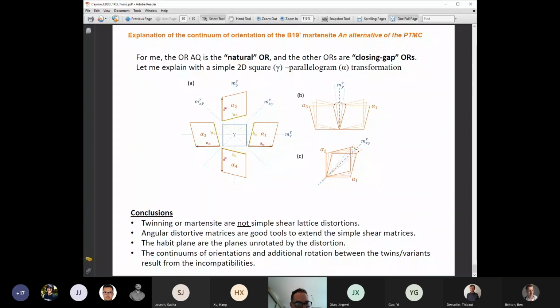If you take only this one orientation relationship, here with this example with the square and the parallelograms, you get only a finite number of variants. But we know from EBSD that there is a gradient of orientation between these variants. And this gradient of orientation between these variants creates additional orientation relationships and a continuum of orientation relationships. They are due to the fact that you need to accommodate the incompatibilities. And the representation on the right explains how you can figure out how to make this accommodation. You look at one direction that is a mirror symmetry, for example, of the parent phase, and it is transformed into two different planes, and then you close the gap to make a parallelism between these planes.